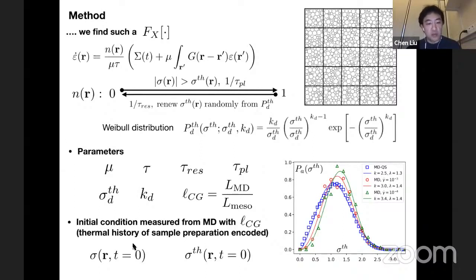and then we should inject the initial condition to run the dynamics, which is just the initial field of local stress, and then the initial field of local thresholds, which can be directly measured from the MD system with a certain given length scale.